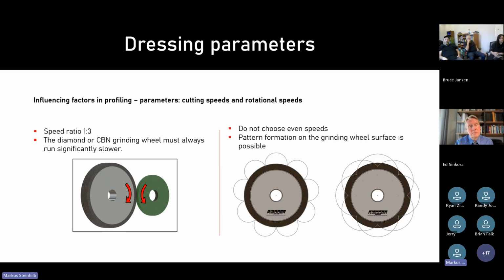Another point are the parameters of the wheels: the chosen cutting speed, and also the selected RPM. At Rigor, we always recommend paying attention to the rotational speeds and suggest a speed ratio of 1:3. So the dressing wheel should always run 3 times faster than the grinding wheel. For example, when you choose 500 RPM for the grinding wheel, you have to adjust 1500 RPM for the dressing wheel. If this ratio can't be achieved, because it's not possible on the machine or something like that, the diamond or CBN grinding wheel must always run significantly slower.